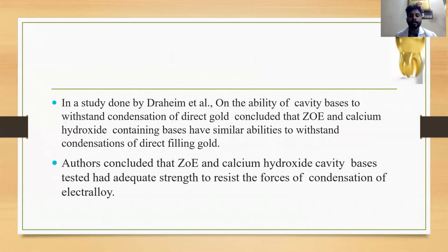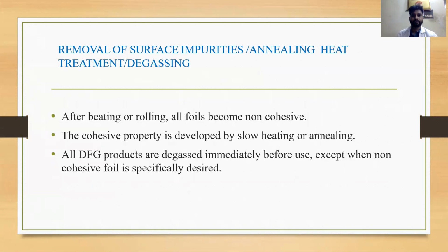The study done by Draheim et al. on the ability of cavity bases to withstand condensation of direct gold concluded that zinc oxide eugenol and calcium hydroxide containing bases have similar abilities to withstand condensation of direct filling gold. The authors concluded that the zinc oxide eugenol and calcium hydroxide cavity bases tested had adequate strength to resist forces of condensation of electralloy.